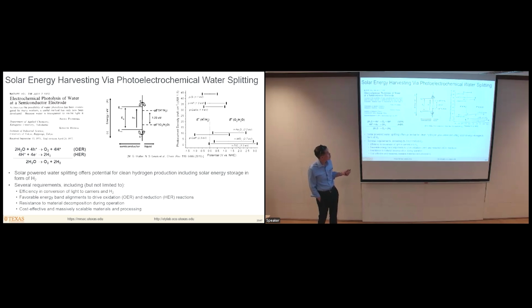Okay, so this is known, but it's an extremely hard problem scientifically and technologically, because there are several requirements that have to be satisfied in order to get this to work. So you need absorber materials that are good absorbers of sunlight. That means you typically want semiconductors that have moderate energy band gaps, band gaps that are typical of solar cells or maybe somewhat larger. So materials like silicon, gallium arsenide, and so forth, and a few others.